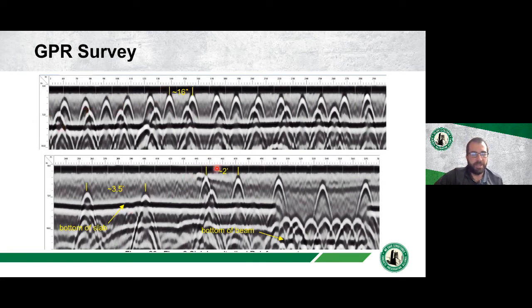Here's another scan. You can see here's the slab, and you can see again post-tensioning in the bottom of the slab, so we can see what the thickness of the slab is. So here's the bottom, here's the PT, here's some conventional reinforcement. And then we can also see in the slab where an integral beam is, you can see the slab bottom changes. Here it drops down to here. So this is where a beam is.